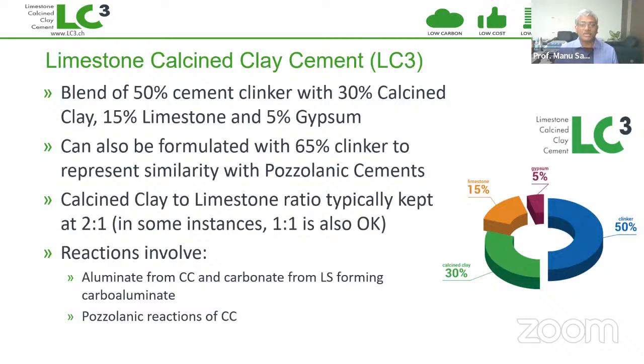The reactions which lead to the unique behavior of LC3 include, among other things, reactions of the alumina from the calcined clay and the carbonate from the limestone. They form additional compounds like carboaluminates, which are very useful in filling up the pores and ensuring that you have a very low permeability in the concrete. Then, of course, the calcined clay, like any other pozzolan, like fly ash or silica fume, can continue to react with calcium hydroxide and lead to the formation of calcium silicate hydrate, the typical pozzolanic reaction that you expect.